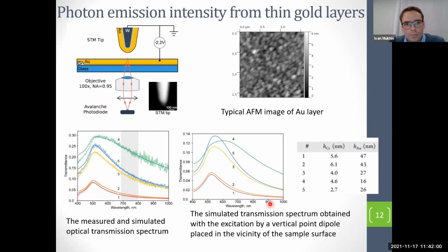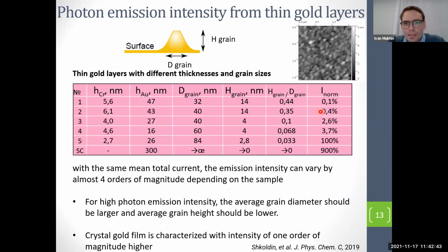To answer that question, we made a numerical simulation. We positioned a point optical dipole under a thin film and collected the transmitted light. You can see that quantitatively these results correlate very nicely, so the answer is positive. Yes, we can use a simple method to compare the signal from different layers. If you have a look at this column, this is normalized on the thickness, on the transparency of our film. This is the normalized intensity of emitted light.